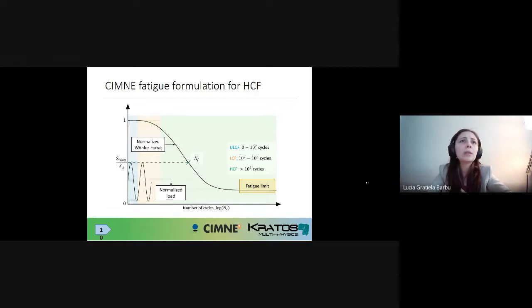So if we take a look, for instance, at a typical SN curve, okay, we normalize it with the maximum tensile strength. And we see that for a specific level of maximum loading, what the SN curve is going to give us is the maximum fatigue life that the material can withstand at that stress level. Okay, when we add into this equation also the fatigue reduction function, what we are doing is obliging it to respect two different conditions. It should begin also at a level of one, which would be the static tensile strength of the material. And this function necessarily has to pass through this intersection point over here, which tells us that we have lowered the strength of the material sufficiently that we are crossing the level of maximum stress. And this is when we are breaking our specimen at that specific material point. After that, the evolution between these two points will depend on the material parameters that we will have to calibrate.